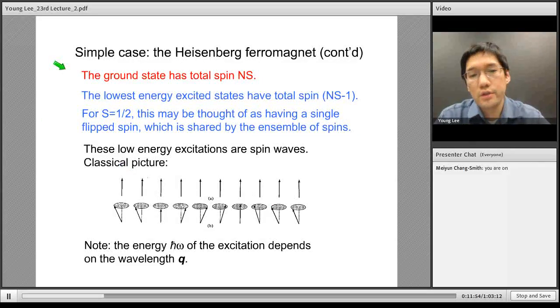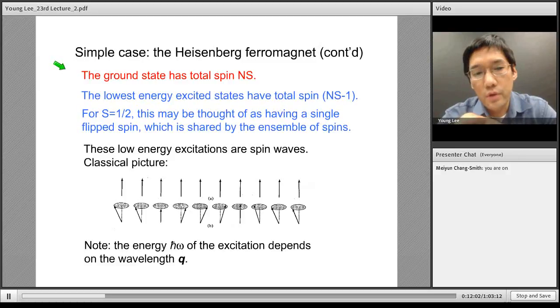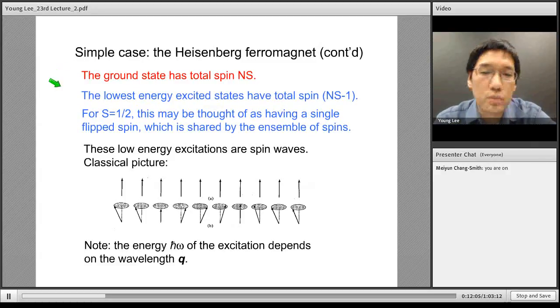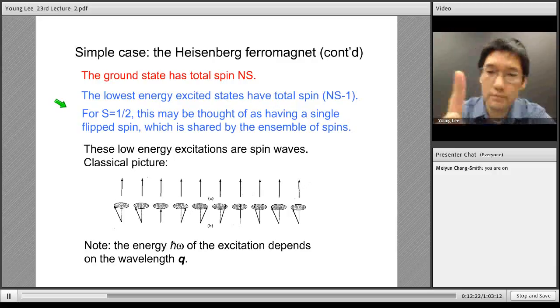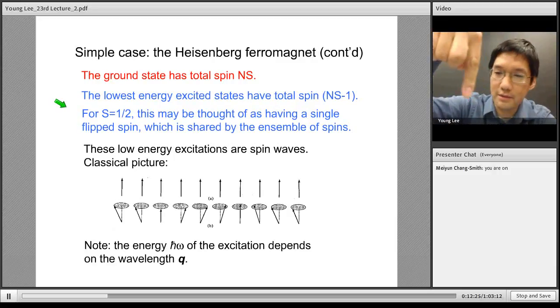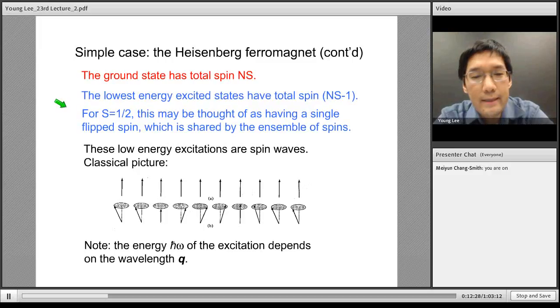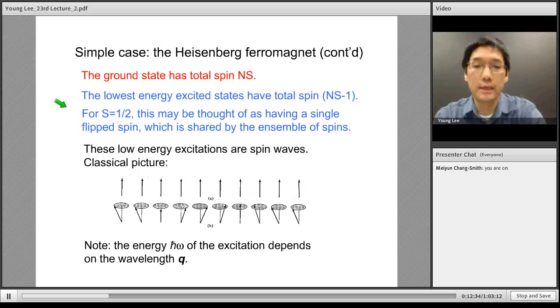Continuing on this, so the ground state is fully polarized. So if we have N spins, the total spin is N times S. So let's think about the excited states. So then the excited states will be the case where you just have 1 unit less for the total spin, so NS minus 1. If you think about this with the collection of spin 1/2 moments, then this would just be having a spin up flipped over to spin down. It's hard to get this on the camera. Okay, this spin flip we can think of being shared by the whole collection of the spins.